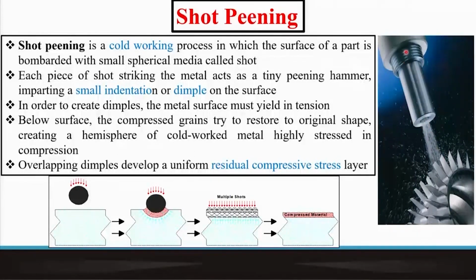So what we need is a gun which will throw these shots at great velocity, and these shots are similar within a very close tolerance limit of diameter, 0.5, 0.6 or even less. They hit turbine blades and fins, which are subjected to such compressive stress development practice, so that the blades develop residual compressive stress and can withstand a very high level of fatigue, even thermal fatigue.